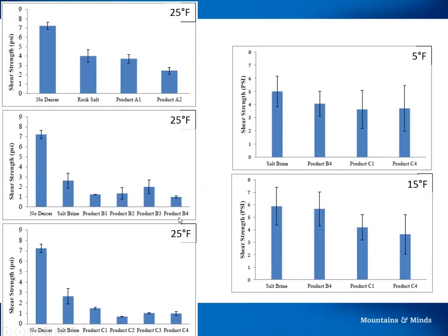Category B products, so these are the agro-based products that were mixed with salt brine. They all performed really well. They all had very low shear strength that was required to remove the bonded snow and ice from the pavement. So these are good anti-icers. Better than the salt brine and way better than the asphalt with no de-icer on it. And the category C products down here, these were the as-received agro-based products. And again, they all performed really well as anti-icers, having really low shear strength that was required to remove that snow and ice from the pavement.